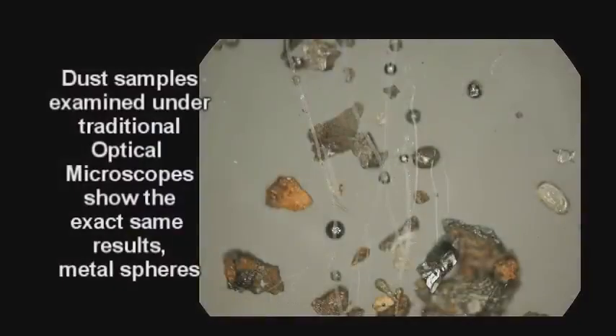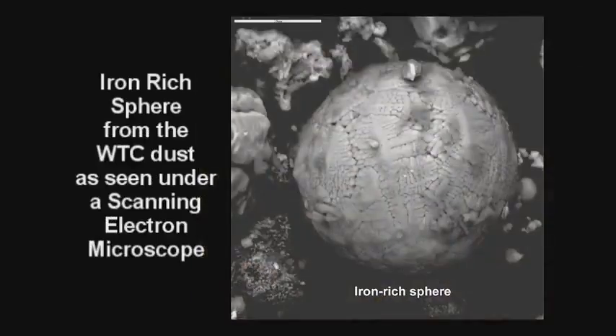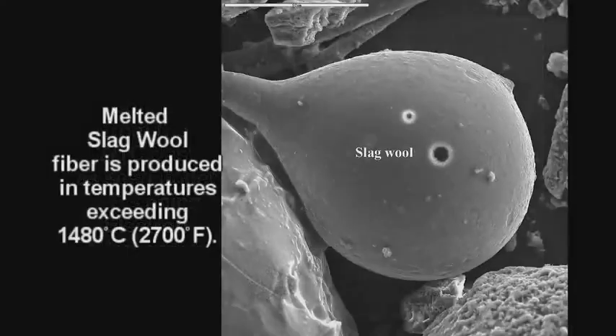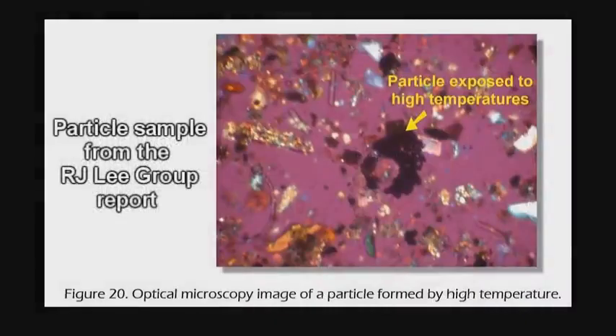Dust samples examined under traditional optical microscopes show exactly the same results: metal spheres. Iron-rich sphere from World Trade Center dust is seen under scanning electron microscope. Melted slag wool fiber is produced in temperatures exceeding 1480 degrees centigrade or 2700 degrees Fahrenheit. Particle sample from the R.J. Lee Group report. Particle exposed to extremely high temperatures.